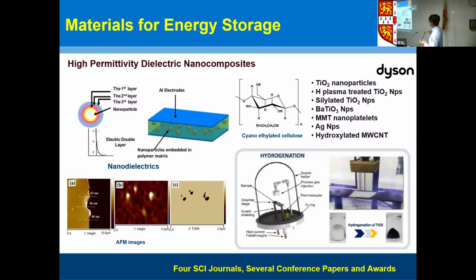So it is on a silicon wafer, and then you fabricate your first layer, an aluminum electrode about 100 nanometers in thickness, and then this is your nanocomposite. So you have your polymers, and you embed your nanoparticles in it, and then the top electrode, the same aluminum electrode, 100 nanometers thick. And then you measure all the electrical properties, probe measurements, and see how it behaves. Luckily, we have all the facilities to fabricate nanoscale devices, and then you can see their electrical properties, their dielectric properties and leakage currents.